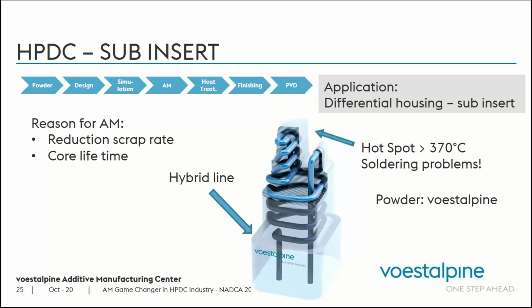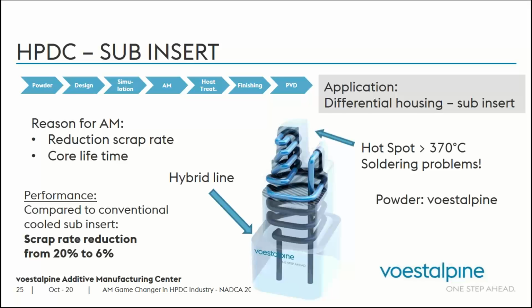Another example, as you can see here, this was for a major OEM in car manufacturing, and an extremely high temperature reduction. If you look at the soldering problem again here on the tip, it was over 370 degrees Celsius at the tip conventionally. This was for a differential housing. So applying additive manufacturing, the scrap rate was reduced from 20% to 6%. That is a huge, huge improvement in scrap rate reduction.